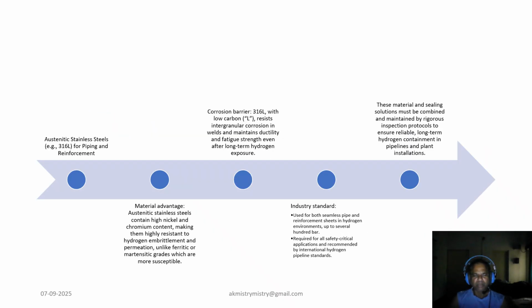Now coming to why austenitic stainless steel 316L material matters, especially under hydrogen duty. Austenitic stainless steels, especially 316L, are industry standard because their nickel and chromium content resist hydrogen embrittlement and permeation. The low carbon, that is the L grade, further resists weld corrosion, maintaining ductility and fatigue strength, essential for safety critical applications, and recommended for any hydrogen pipeline environment.